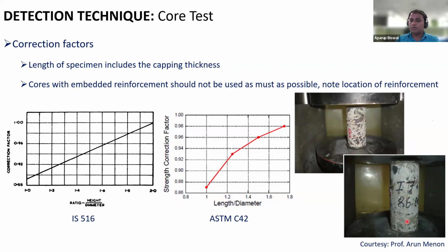Here, the minute crack is visible. That's where the crack is expected to happen, and that's how the failure is expected to happen. Or you should expect a normal cylindrical failure, which a normal cylinder does for a normal core which you have tested. If your failure pattern is random, let's assume I got a shear here, you should not take that as the result for the core test, because that is not the proper failure. Or maybe we got a crushing at these localized regions.